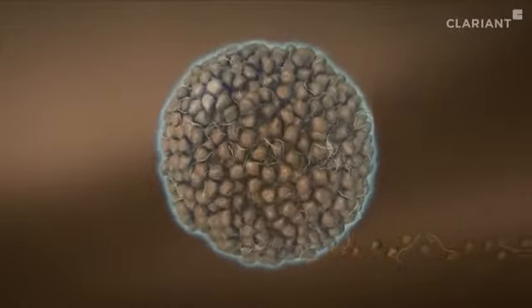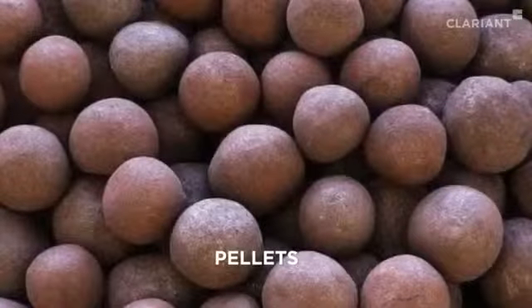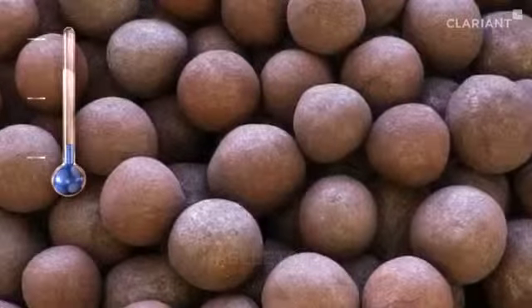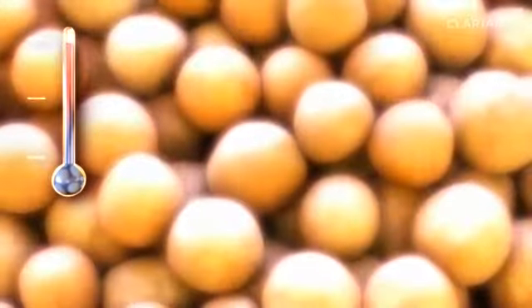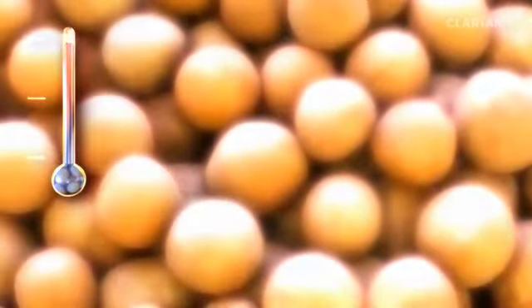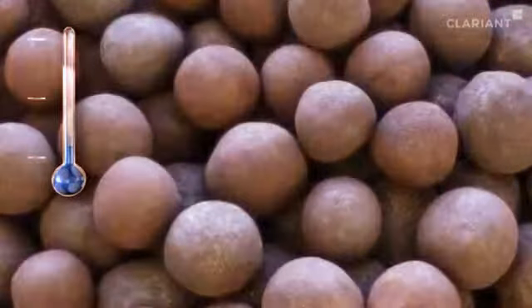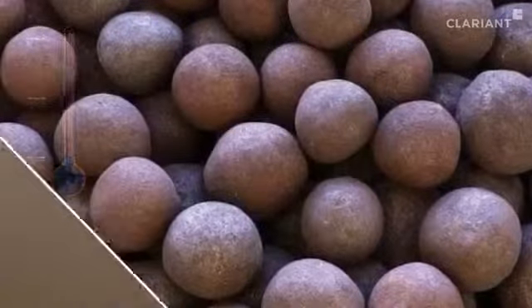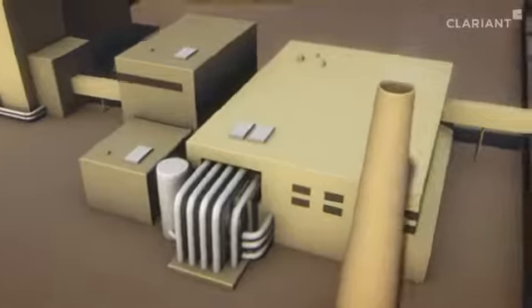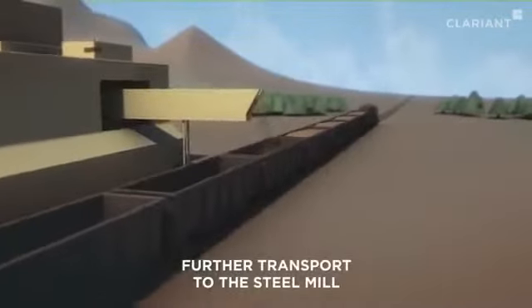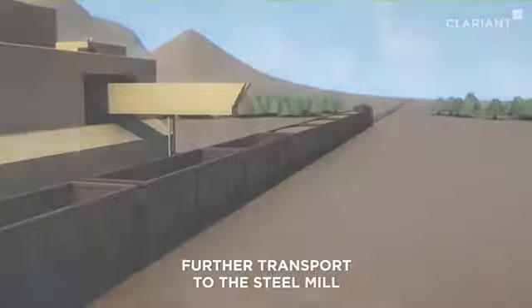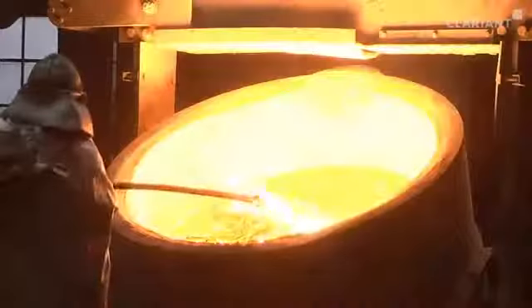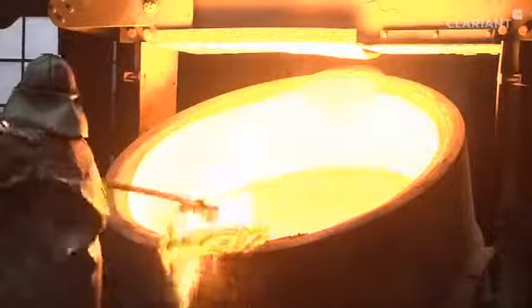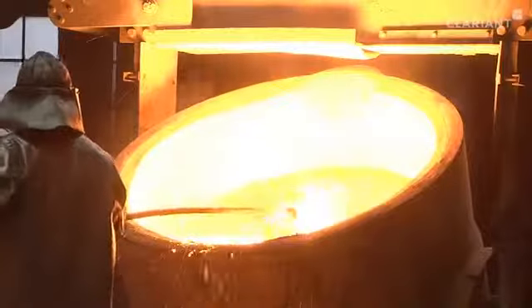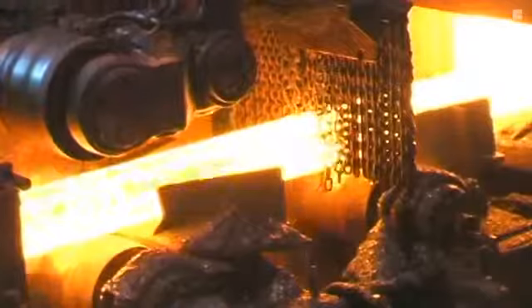Thus, in comparison to conventional material, the treated pellets are more robust and less susceptible to cracking and breakage. Reduced water content means less heating in the pelletizing furnace during a final preparation step, where the pellets are roasted at high temperatures. After cooling down, the iron ore pellets are ready to be shipped. Ultimately, they reach the steel mill. By reducing the silica content and allowing for more iron, the pellets are more valuable.